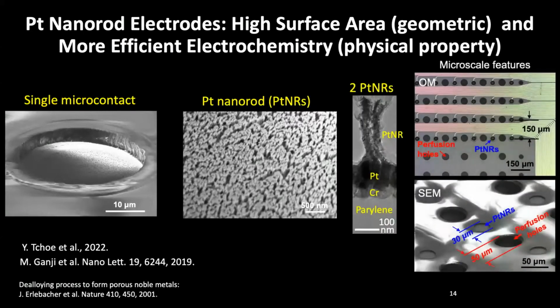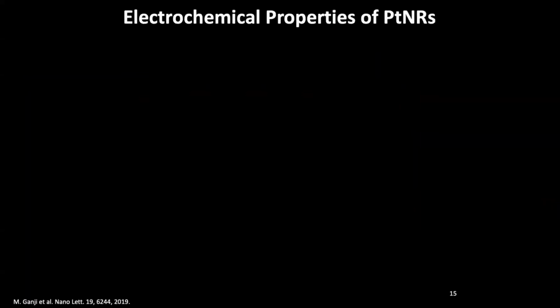And here we're looking at a picture of the device, and below an SEM image where you see perfusion holes in between the platinum contacts. This is on the right-hand side of the slide for those who are watching by Zoom. And on the lower right, we're seeing an image of the device. It's 10 microns thick. The platinum contacts are usually 30 microns in diameter, and perfusion holes allow perfusion of CSF from underneath the grid so that we have that intimate contact with the surface of the brain.